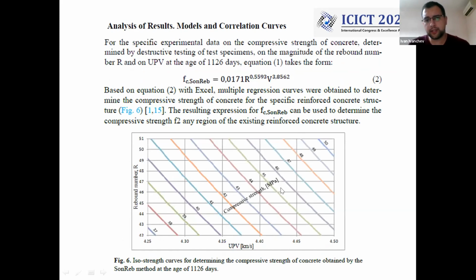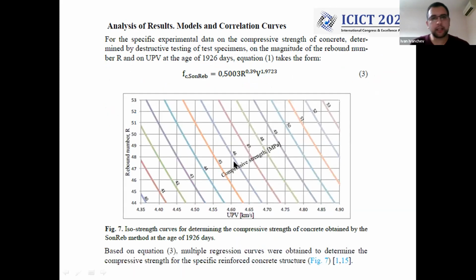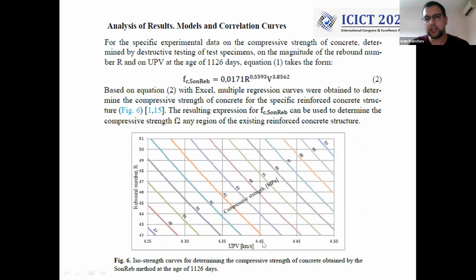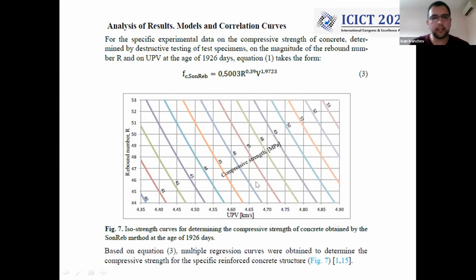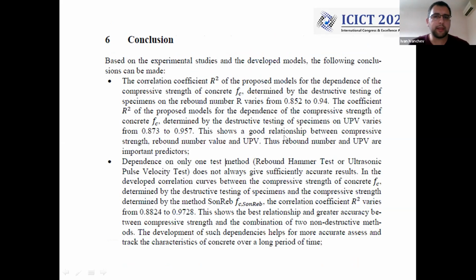And the last thing which is done here is iso-strength curves, which are performed for the 2 days of examination. They are very convenient because we may not do a destructive or some kind of invasive test on the structure. We can make only non-destructive measurements of the ultrasonic pulse velocity, which is the x-axis, and rebound number, which is the y-axis, and we can see from these iso curves the predicted strength via the SonReb method. And as a conclusion, I may skip this. If you have any question, you can ask me. If I have time, I will tell the conclusion, as you decide.